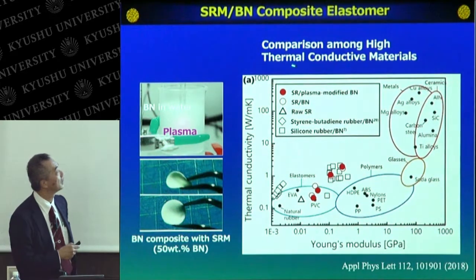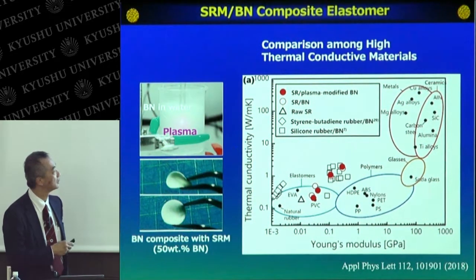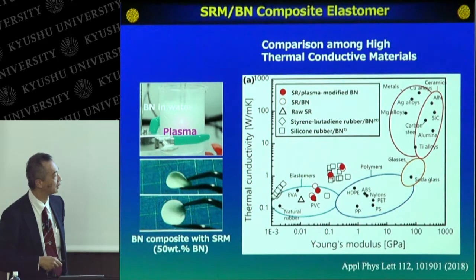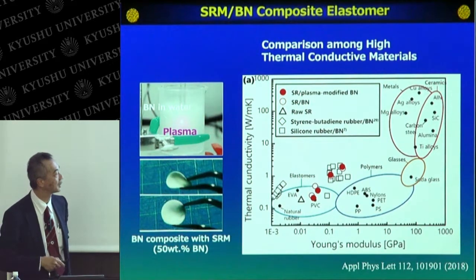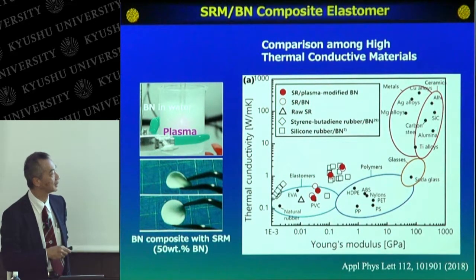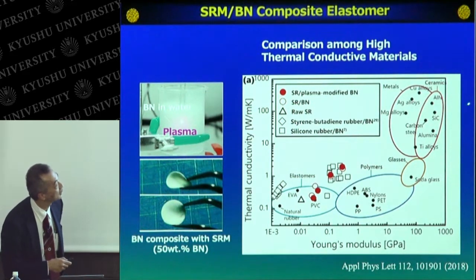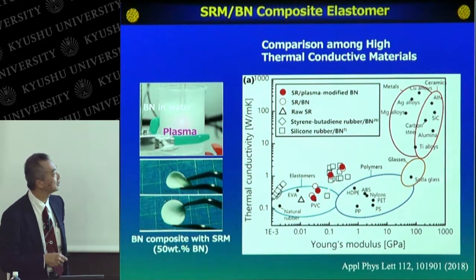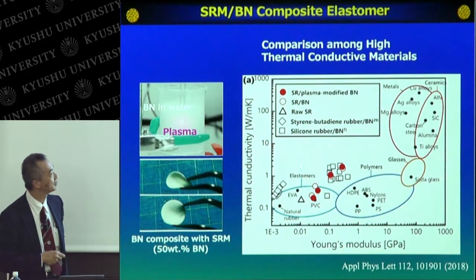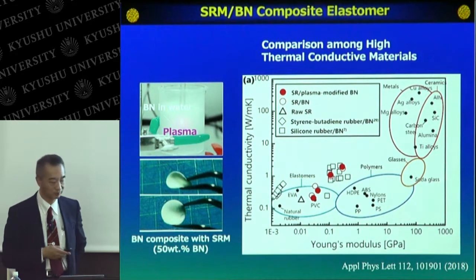This shows the dependence of thermal conductivity on the Young's modulus. So higher thermal conductivity is achieved at the high Young's modulus materials, such as silicon carbide or alumina or something like that. But we developed relatively high thermal conductivity elastomers at lower Young's modulus.